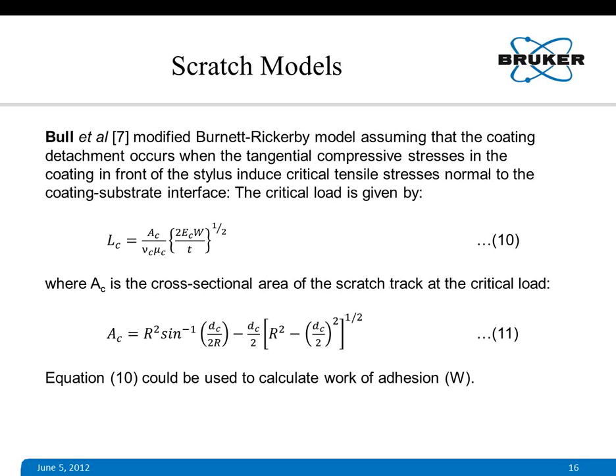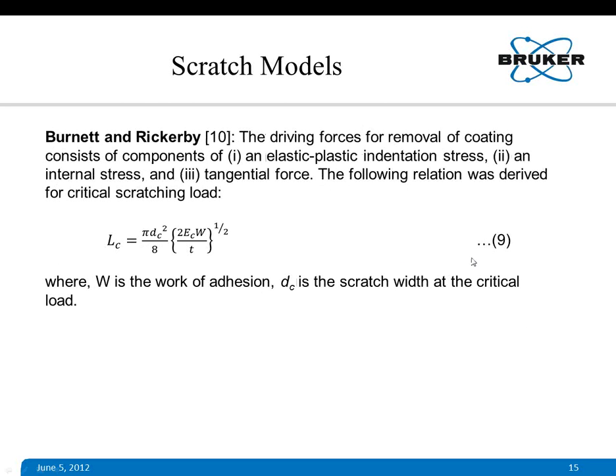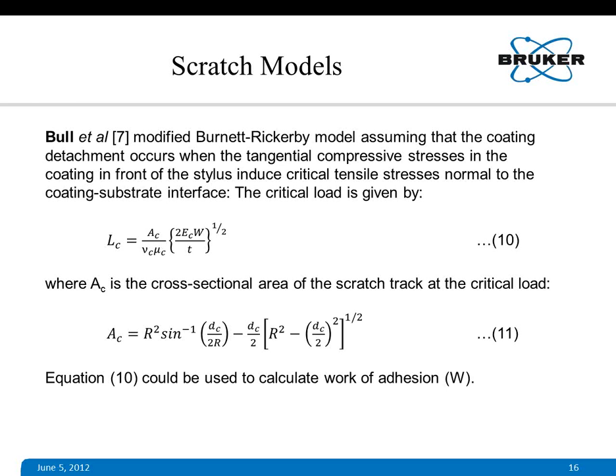Bull et al., S.J. Bull, they have worked a lot on this coating system, and they define critical load as they replace basically this area term in equation 9, pi d square, as AC by nu c into mu c, where mu c is the friction coefficient. They also put for friction, or it is also called drag coefficient, friction drag coefficient. And A is the cross-sectional area of the scratch track at the critical load. AC is expressed in equation 11. Using equation 10 and 11, this is the total model, we can calculate the work of adhesion.